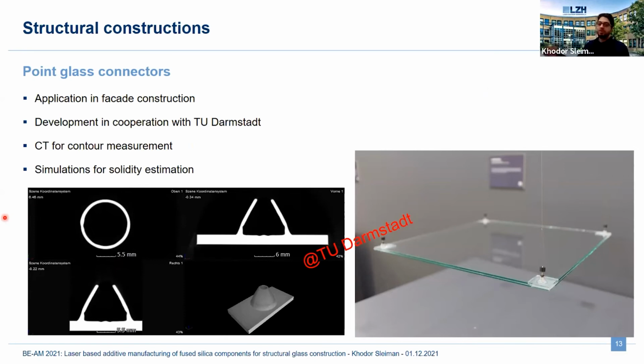TU Darmstadt conducted CT scans of this conical point glass connector for us, and also conducted simulations for solidity estimations, and then we could laminate those point glass connectors onto a glass window to show that these printed glass structures can actually hold a real load.